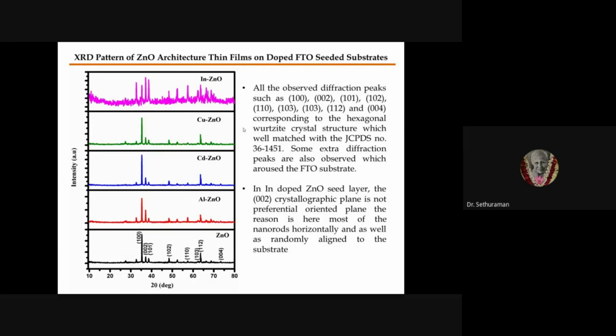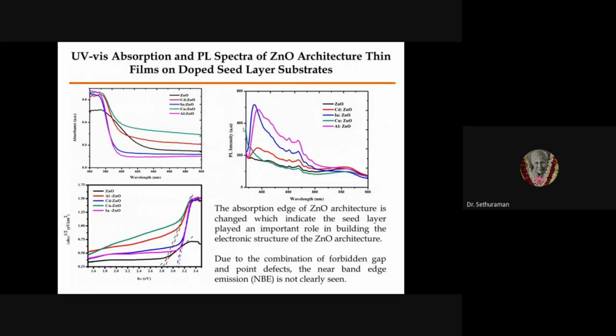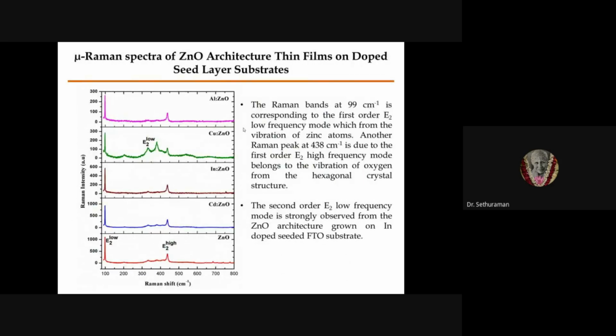The 002 orientation crystallographic plane is the dominant one for the growth of nanorods on the surface of the seed layer, for the different group zinc oxide seeds. This is just UV absorption and Raman on the micro-rods, to confirm the substrates as well, and then frequencies and more.